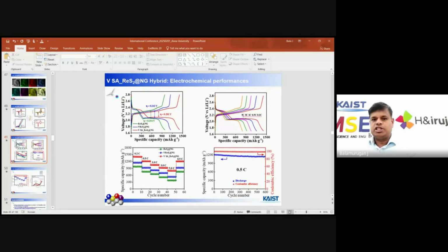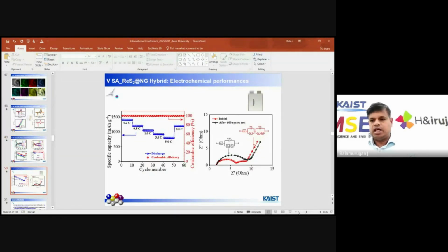And we also do the charge discharge process. You can see when compared to the other materials, the vanadium material gives the highest specific capacity and close oxidation reductions. We also do different C-rate values, for different current densities. When the current density increases, the specific capacity slowly reduces, but you can see the rate performance compared to the other catalysts: the vanadium single atom based catalyst gives higher rate performance, higher durability and higher coulombic efficiency. So from the studies, we can say this about the device.